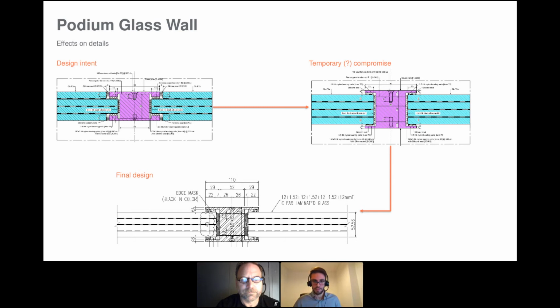Unfortunately, even if we submitted together with the contractor, that by the way is GNM Engineering, which supported quite heavily in these amendments, we submitted lots of detailed calculations, again a detailed brick model, to show that the stress in the interlayer, because this was the main concern from the approval authority, was within quite decent limits, and the safety factor was quite high. In our case, it was around 11 compared to the strength of the SGP interlayer calculated at 50 degrees, so clearly the conservative one. But unfortunately, we had to give up on these details.